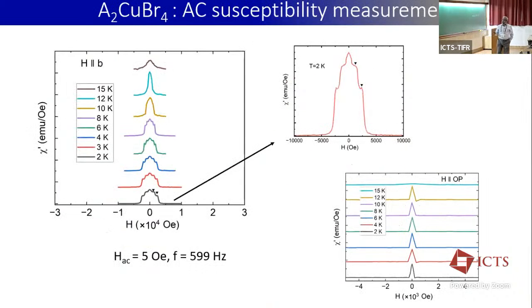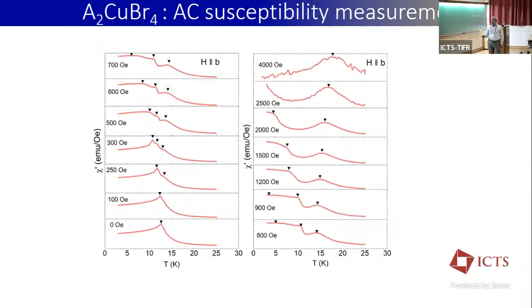And if you look at the bromine sample, it is much more interesting. You look at H parallel to B, and this is a zoomed-in view. Besides your main transition, where you typically see a peak, there are two other transitions here. Along the out-of-plane direction you do not see them, because there is nothing there. And similarly, it is not only one peak.